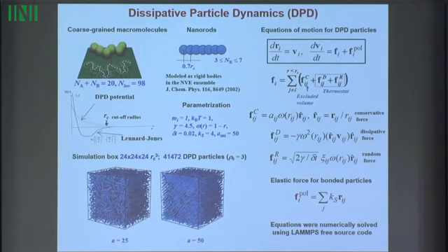And then my collaborators from the Russian Academy of Sciences and the University of Munich also made dissipative particle dynamics simulations of these systems to see if this is something similar to the theory. In this case, the block copolymer was modeled by a chain composed of 20 spheres, depending on how many spheres are in each block. And then the nanoparticle was a rigid object composed of 3 to 7 spheres. So then a standard dissipative particle dynamics simulation with a reasonable system size has been undertaken.